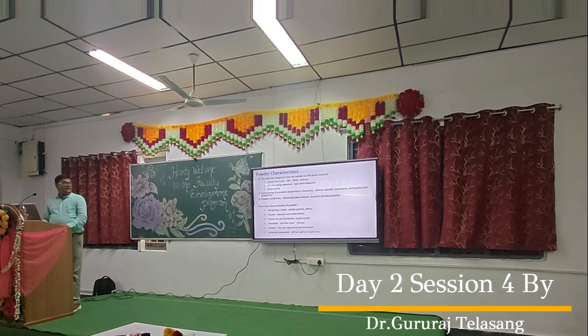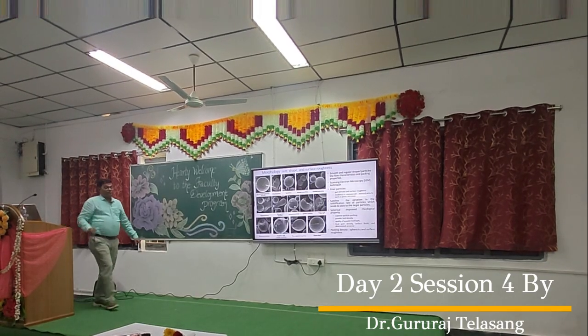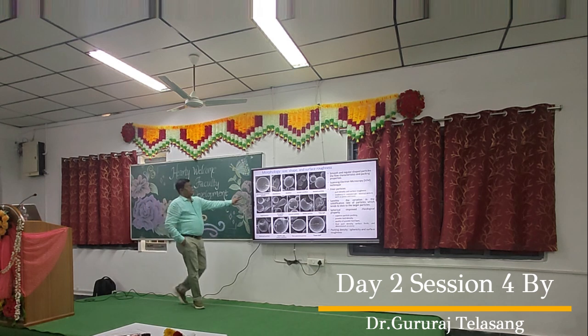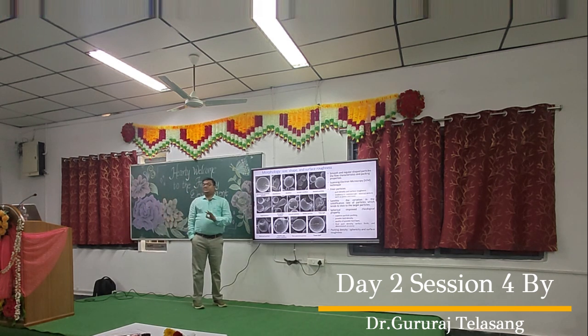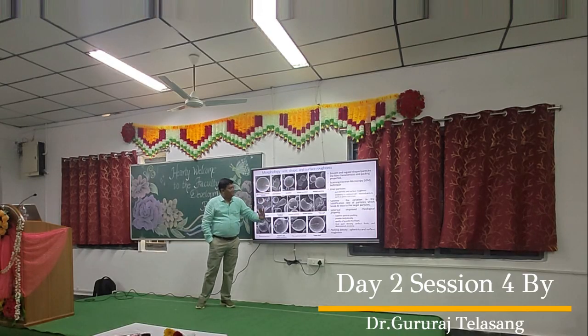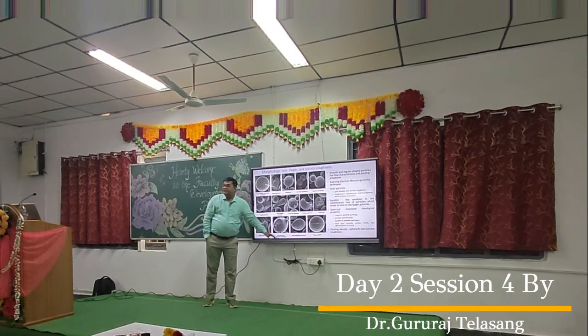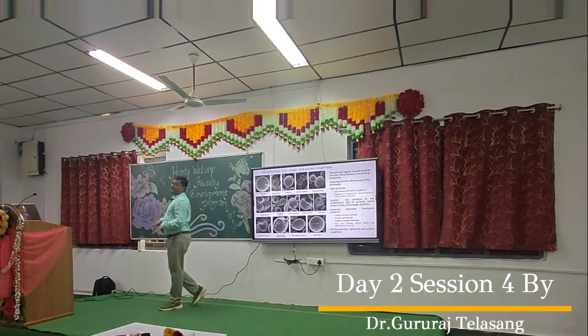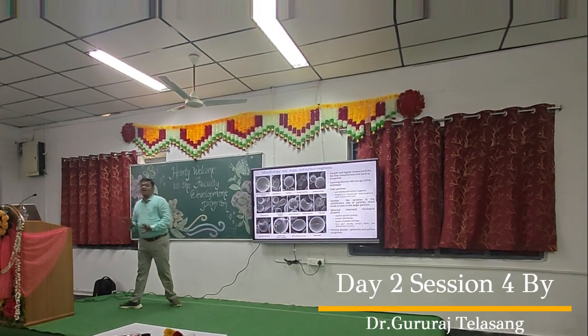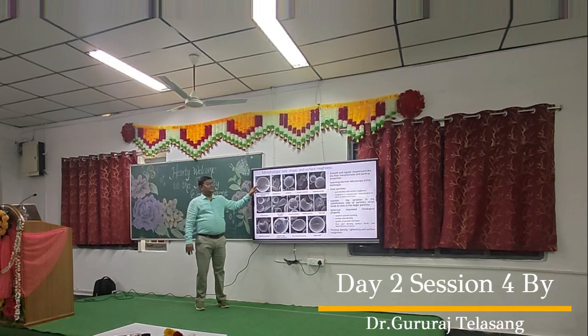So these are all powder characteristics. When you make the powder, if you are getting this, then it is very good. But it's not always that you will get this. Sometimes you will get this, sometimes inside porosity, broken particles, elongated particles. These are all defects in the powder making process. But what we want is this or near this.